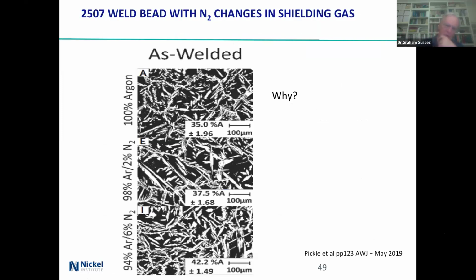This is as welded and changing the gases. 100% argon, 35% austenite, 98% argon, 37, and 94% argon, 42 austenite. Why? Because the other thing that's there is nitrogen, and nitrogen is austenite forming.